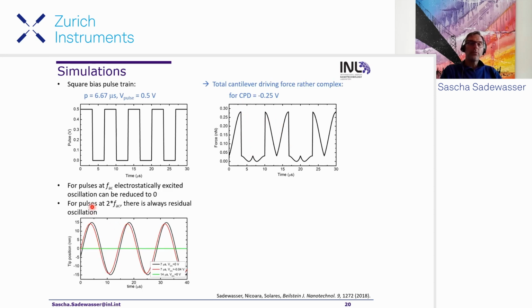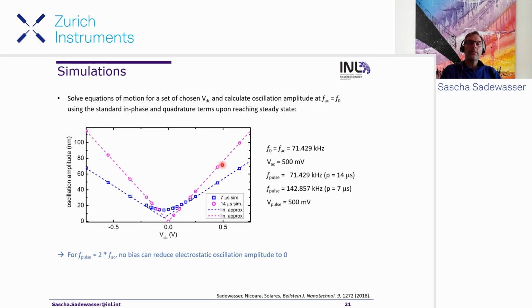And when you try to apply a compensating voltage to reduce this, you can actually not reduce the electrostatically excited oscillation of the cantilever completely, if you have pulses at 2 times the AC frequency. This is how we evaluate those results. We determine the amplitude of the electrostatic excitation as a function of different applied biases. This is essentially the work that our Kelvin controller normally does. And then we see this amplitude decreases to zero if we are not at 2 times the frequency, but if we are at 2 times the frequency of the AC voltage, we are not able to reduce this to zero. So we get a slightly offset minimum. This is about a 40 millivolt difference to where we would expect it to vanish at zero.